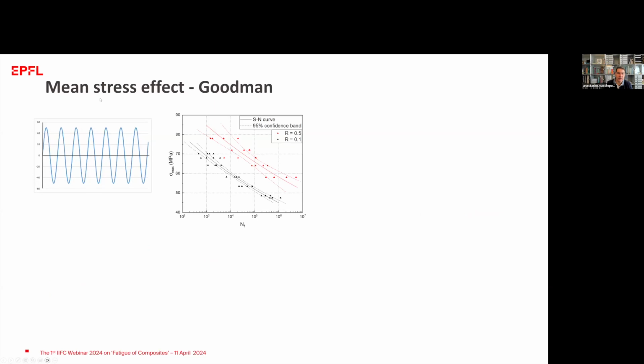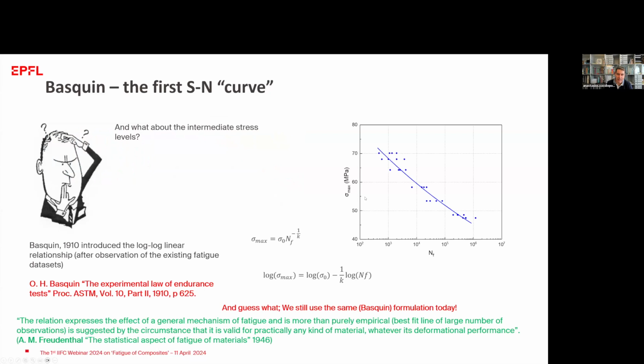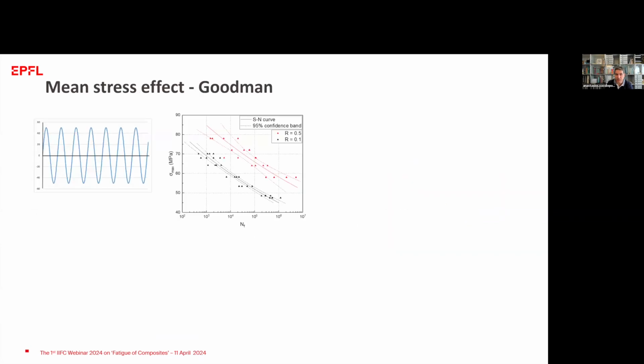So then we had the effect of the mean stress. You know that what we described up to this point and what Wöhler did, it was, as we said, a rotating axle with a load at the end, which means that we had tension and compression of the same amplitude, which means that the mean stress here is 0 in this testing. So if the mean stress is not 0, so for example, if we test only at positive stresses or only at negative stresses, then there is a mean stress effect. And we've seen today that there is a significant effect of the mean stress, especially for composites. And good for us, there was Goodman,